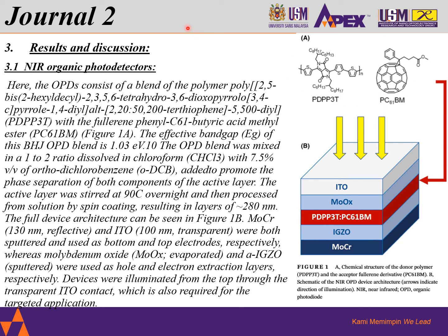The effective band gap Eg of this BHJ OPD blend is 1.03 electron volt. The OPD blend was mixed in a 1:2 ratio dissolved in chloroform with 7.5% of ortho-dichlorobenzene, which promotes the phase separation of both components of the active layer. The active layer was stirred at 90 degrees Celsius overnight and then processed from solution by spin coating, resulting in layers of 280 nanometer. The full device architecture can be seen in figure 1b.